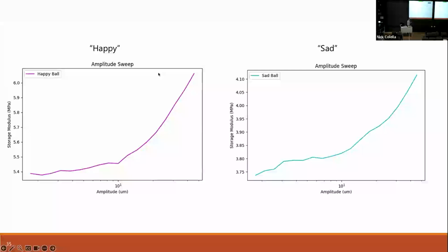So this is what's called an amplitude sweep. This is what we do first. We generally want to measure in the region where we have consistent modulus over a range of amplitudes. That's what's called the linear viscoelastic region. What's happening there is the chains are pushing together and then springing back to their original conformation. We're not doing any permanent deformation on the material. Once we get past that, then we start to break bonds or break chains, or change our physical crosslinks, and then we're doing some actual change to the material. We're out of the linear viscoelastic region. We're really starting to deform the sample. And then we're not characterizing the sample, we're kind of characterizing our measurement. So we want to stay in this linear viscoelastic region.